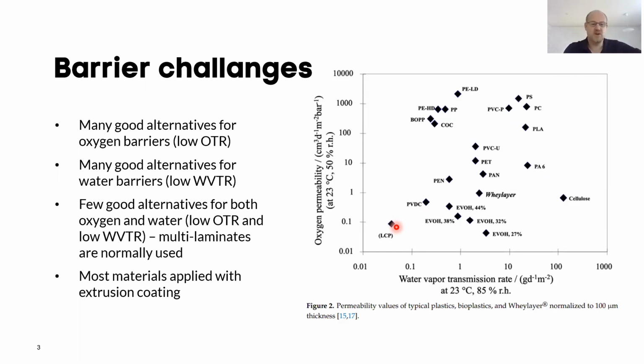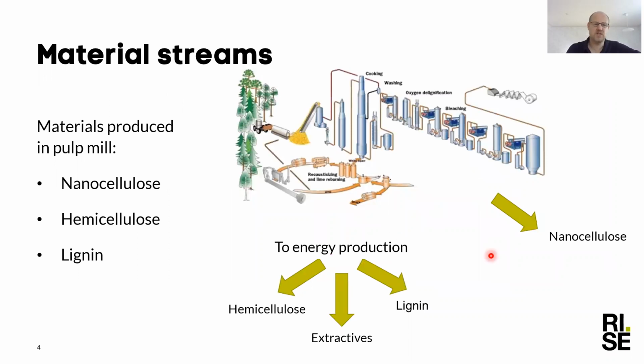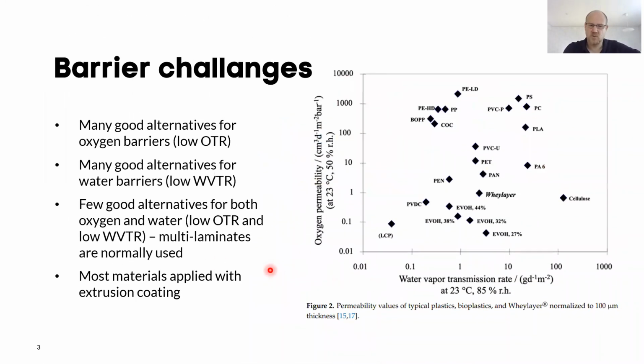Most of these materials are applied with extrusion coating. I should also say that if we look a little bit at what we're trying to use to replace fossil-based plastics, normally you would make a multi-laminate consisting of a couple of these plastics, like EVOH and polyethylene, to get a good water and oxygen barrier.